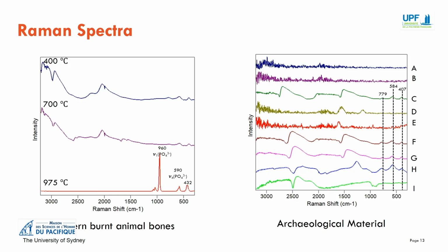The spectrum from the sample burnt at 975 degrees Celsius is of good quality with a high signal-to-noise ratio. It is a much simpler spectrum compared to its infrared counterpart, and the bands are attributable to the inorganic matrix. The quality of the data from the archaeological material is highly variable. The Bravo Raman spectrometer has a built-in fluorescence mitigation algorithm, but it wasn't able to completely counter the effects of fluorescence, as can be seen in spectra C, F, G, H, and I.